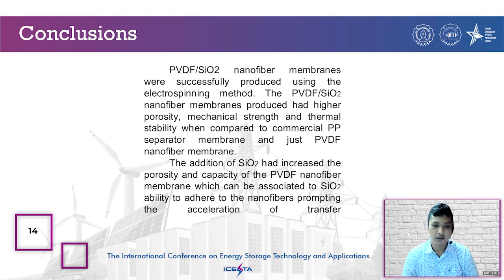And the last one is the conclusion. PVDF SiO2 nanofiber membranes were successfully produced using the electrospinning method, and the PVDF SiO2 nanofiber membranes produced had higher porosity, mechanical strength, and thermal stability when compared to commercial PP separator membrane and just PVDF nanofiber membrane. The addition of SiO2 had increased the porosity and capacity of the PVDF nanofiber membrane, which can be associated with SiO2's ability to adhere to the nanofiber, prompting the acceleration of ion transfer.